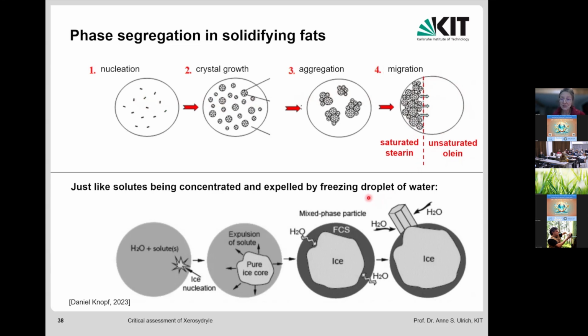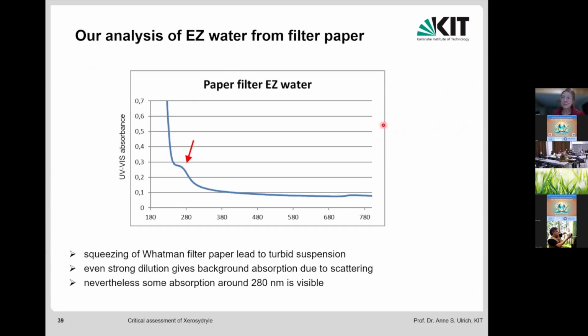And in fact, as water scientists, you're very familiar with what happens when a droplet of water freezes which is contaminated or just containing some solutes. Ice does not want to accommodate any solutes in a crystal structure. So when a water droplet cools down, ice nucleates, a small ice crystal grows and excludes the solute from the ice, pushes it onto the surface of the water droplet. So the surface is now enriched in the solute. In the case of the lipid mixture in the melting state, this would be enrichment in the unsaturated oleic acids and polyunsaturated ones.